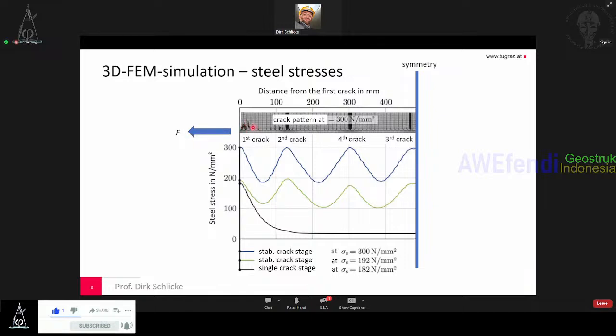there's some internal cracking, it looks like, and after a certain length you get another crack and another crack and another crack. But for this you also need to increase the force. So if you start pulling, you start having only this opening of the first crack, and then the force is introduced back to the concrete so that the steel stress decreases. After increasing the force, you get a second crack, then a third crack, a fourth crack.